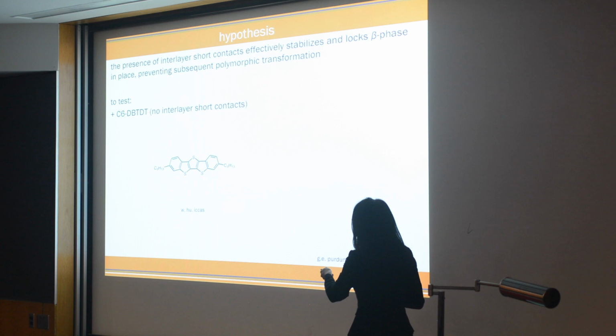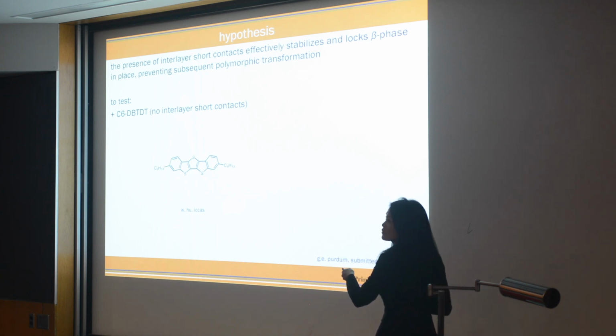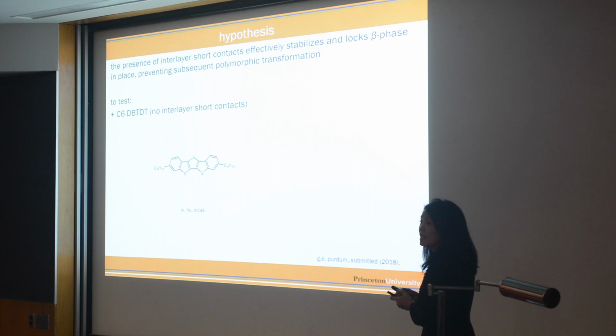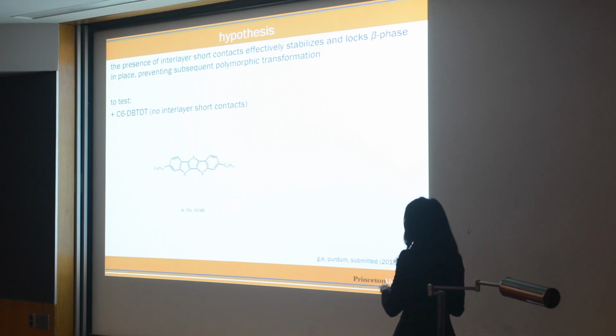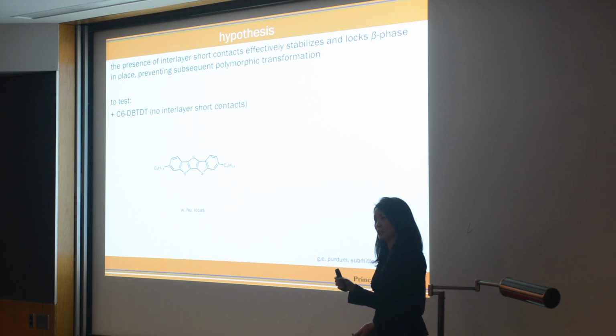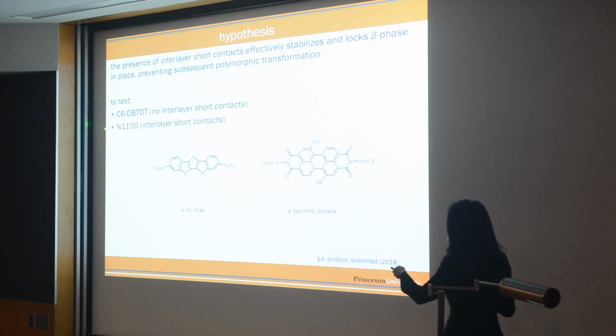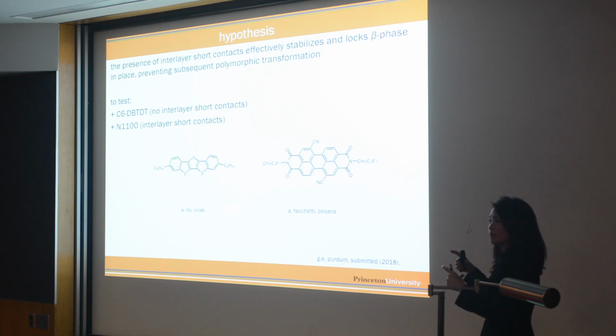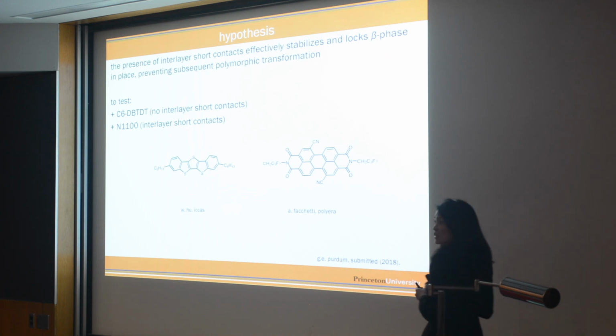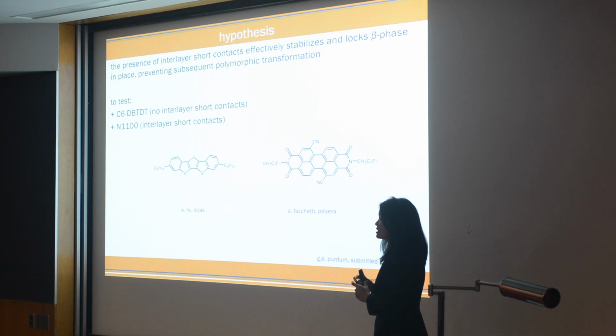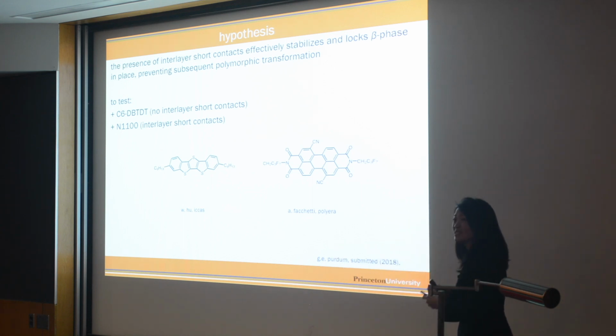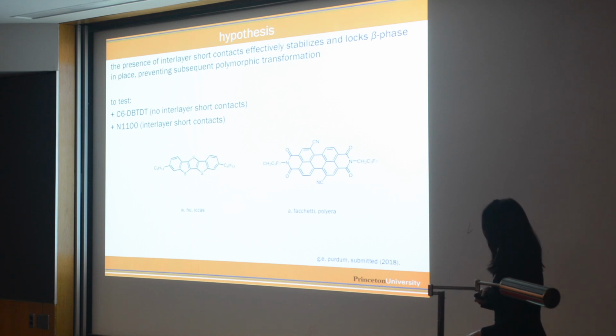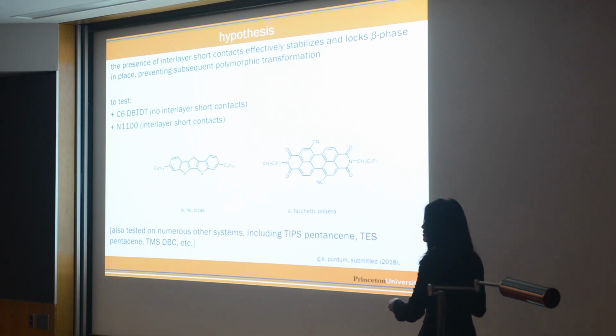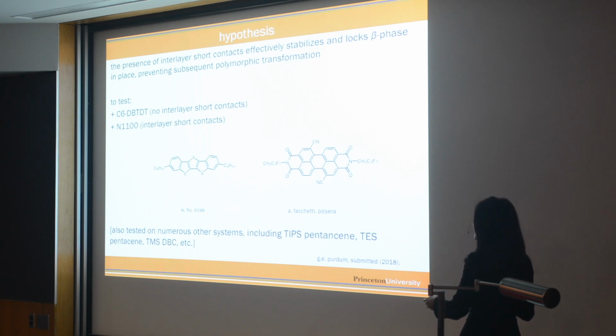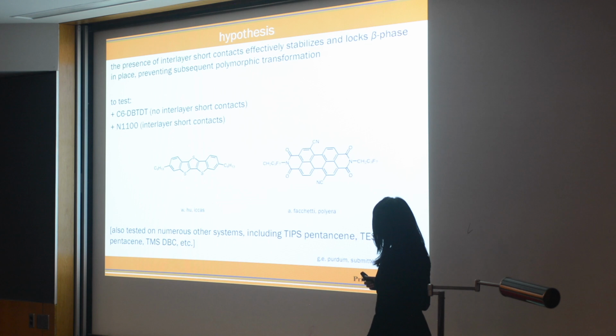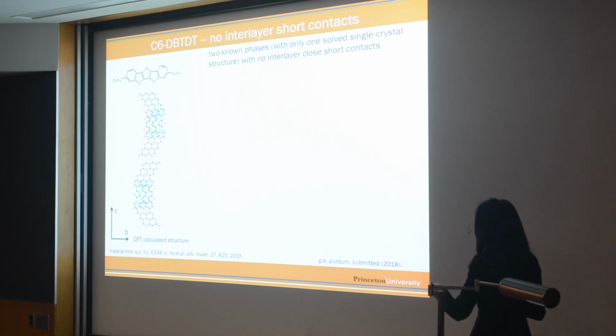So to test this hypothesis, we decided to look at several other organic semiconductors. We decided to look at this DBTDT first because we know its crystal structure has no interlayer short contacts. And so by definition, if our hypothesis is correct, we should be able to transform in and out of its polymorph. We also tested this N1100. This is a perylene diimide. It's got a bigger core. It's got interlayer short contacts. And this, again, we can find out from looking at the crystal structure itself. And so by definition, we should be stuck in its polymorph with N1100. And in the meantime, we've tested numerous other systems, including TIPS pentacene, TES pentacene, TMS DBC, et cetera, et cetera.